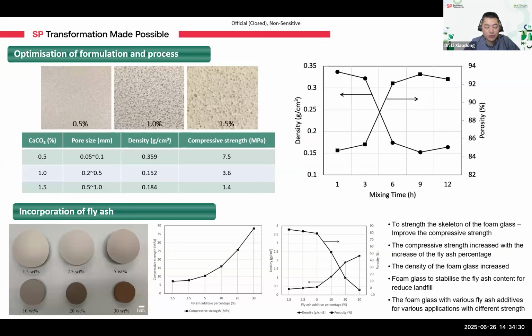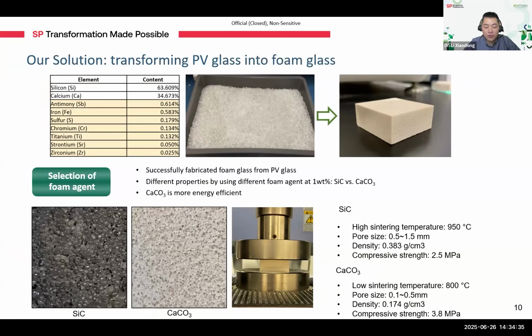Too small pores don't insulate well, and too large pores will weaken the structure. Uniform pores are ideal for strength and performance. So for example, when using silicon carbide as the foam agent, we observed large and uneven outer pores, making the foam glass brittle. On the other hand, calcium carbonate can produce uniform pores and stronger samples. Plus, it requires 150 degrees Celsius less energy during processing, making it a greener choice.